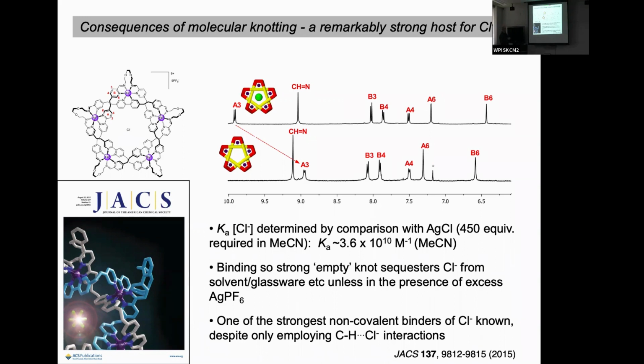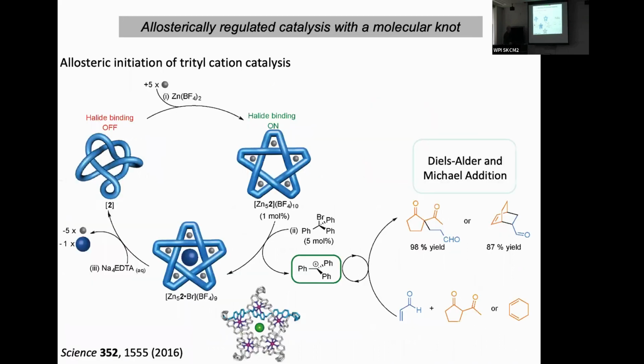And so this binding is so strong that these empty knots will actually sequester chloride ion from solvent, from glassware, unless you keep them in the presence of silver salts or other halophilic sources. So this knot is actually one of the strongest non-covalent binders of chloride ion that's known, and we can use that in its chemistry. So if we have formed our knot, we can actually remove the metal ions by treating it with sodium EDTA, and then the knot is completely stable, but it doesn't have any well-defined form.